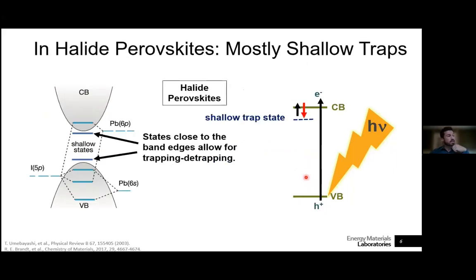In perovskites, the top of the valence band is mostly formed by antibonding orbitals, whereas the bottom of the conduction band has mostly a bonding character. As such, if we remove an atom, we form either states within the valence and conduction bands or very shallow defect states nearby these band edges. This makes it so that carriers are more easily detrapped by thermal contributions, and non-radiative recombination is less important.